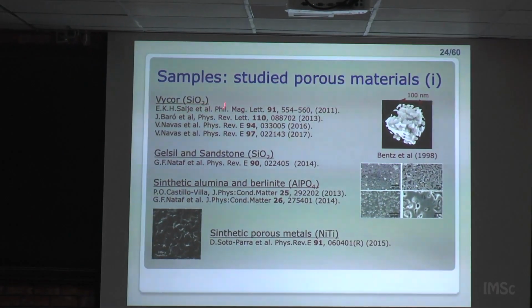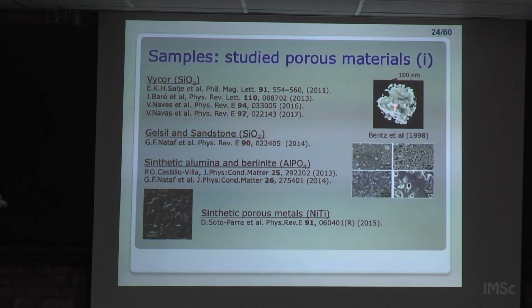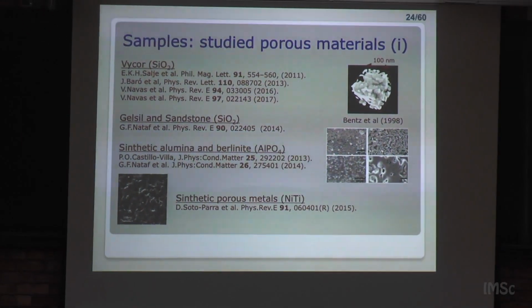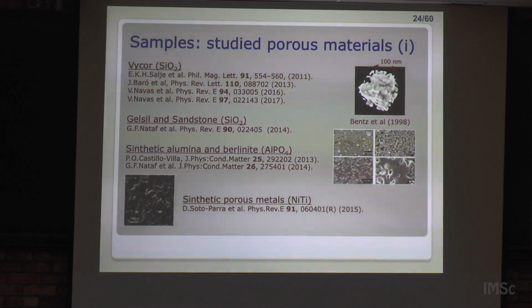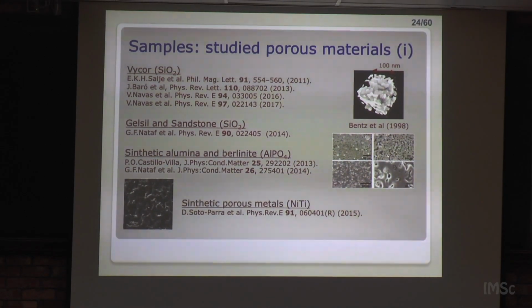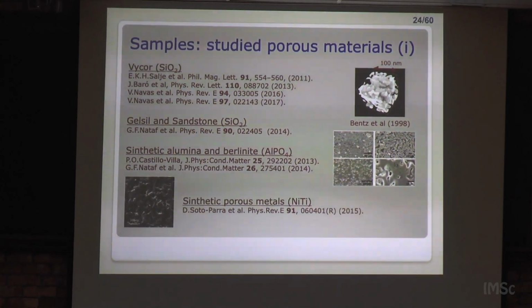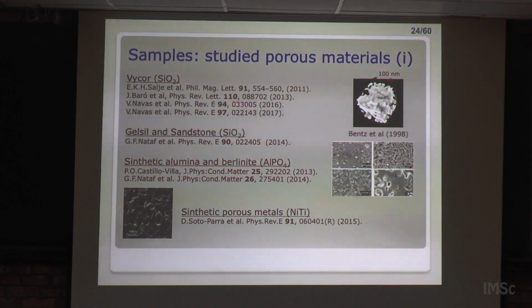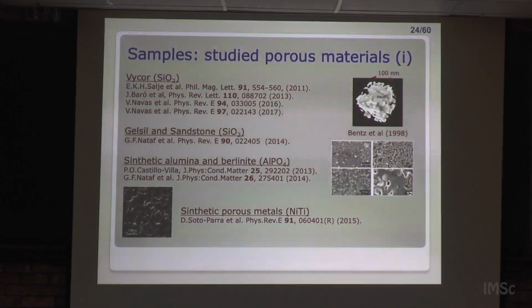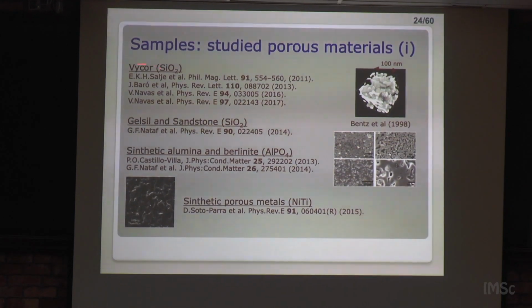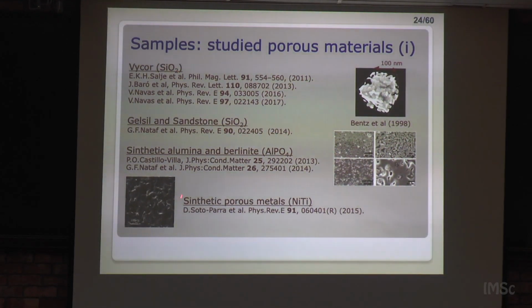Okay, so I was saying that this is porous at the nanoscale. We have worked a lot with this material because, as you will see, the results are really very nice. They agree very well because this is a synthetic material. It's very clean. It's SiO2 in a 99% proportion. Then what happens is that this material is not produced anymore. So now we had to change to another.